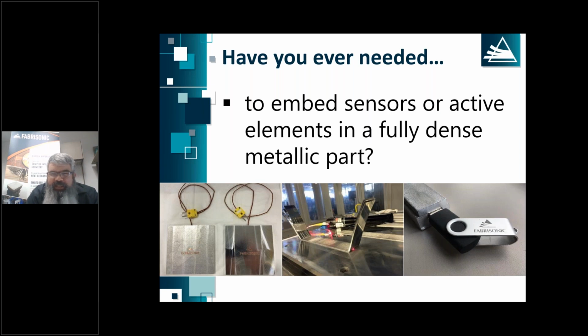Most of the time, that pretty much anything happens to be some sort of electronics package, and I'd say 75% of the time, that's some sort of sensor. What we do is we print metal to a certain height. We come in with that CNC mill. Again, all of our systems are hybrid. We mill away a little channel, a little groove. We drop in that electronics package, and then we continue welding right over top of it. Because it's so low temperature, because it's such a soft process, we don't damage those complex electronics packages.